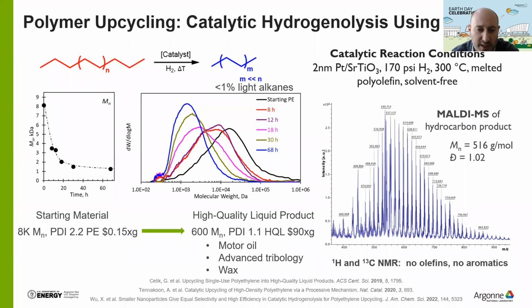But why was this a real breakthrough in this kind of chemistry? Because we didn't reinvent the wheel. We compared, for example, the same catalyst, platinum on different supports, such as alumina or silica. What we notice is that the strontium titanate, particularly the platinum strontium titanate, doesn't produce any byproduct, meaning the amount of light alkanes, C1 to C8, was really minimal. That means that 100% of the plastic bag can be transformed, with 99% transformed into a lubricant or a liquid. Compare, for example, to platinum alumina with the same particle size, where 20–30% byproduct can be light gases. And this was really a breakthrough.